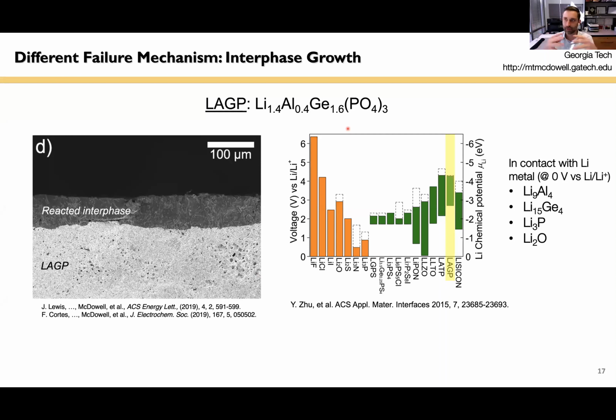This is a problem with many solid electrolyte materials. This is a plot from a modeling study by Yifei Mo's group at Maryland, where they predict the electrochemical stability of a variety of different solid state electrolyte materials. These are the green bars here. And you can see that the overall voltage stability on the left here is quite limited for most of them. LLZO is the only material that has a voltage stability that approaches the potential of lithium metal, but it doesn't even get there thermodynamically. So basically what this means is that your solid electrolyte is not going to be thermodynamically stable in contact with lithium or cathode materials in many cases. And so you expect to have some sort of structural evolution at the interface, which can be quite complex.